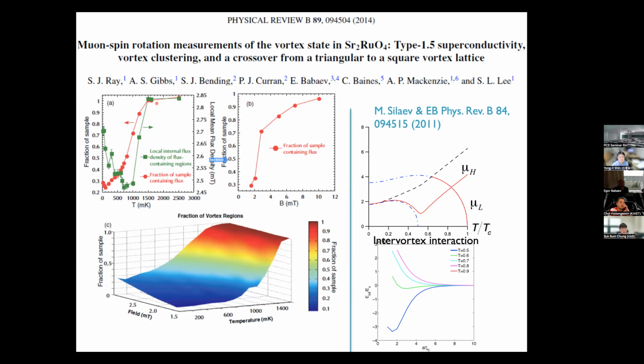If you look at this, so basically cool below TC, it's not like you dilutely get more and more superconductivity and uniformly dilute the vortex lattice more and more, but rather you get phase separation: the fraction of the sample that contains flux drops, and the fraction in the Meissner state grows. So that's consistent with the semi-Meissner state. It's consistent with the phase separation I talked about, but phase separation could also happen for other reasons. If the sample is bad and you have pinning defects, you can have this type of phase separation for artificial reasons, from pinning. But this experiment has shown that it is not pinning which is at play.